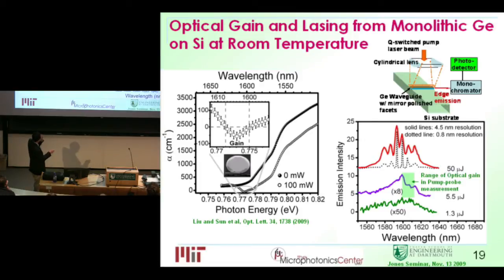As you go to a really high pumping power, you see the sharp lines show up. Actually, this red curve is already limited by the resolution of the spectrometer. With higher resolution, you can see very narrow lines. So this is a sign of lasing. So we think if we further improve that, we could do an electrically pumped laser. So you turn on your switch, and this will lase. And then you can integrate many of these lasers on silicon at low cost.